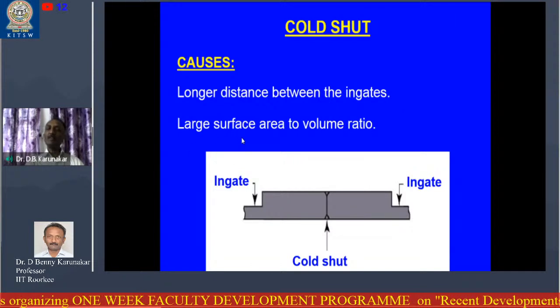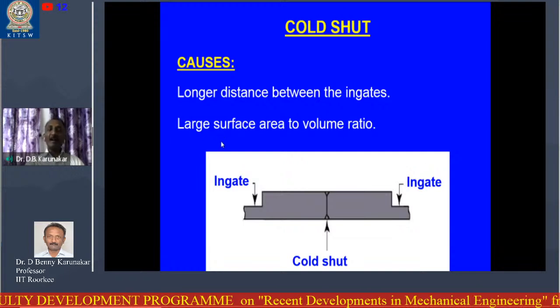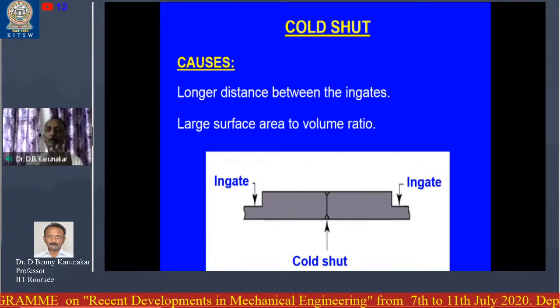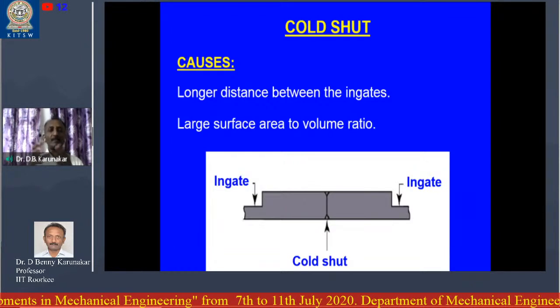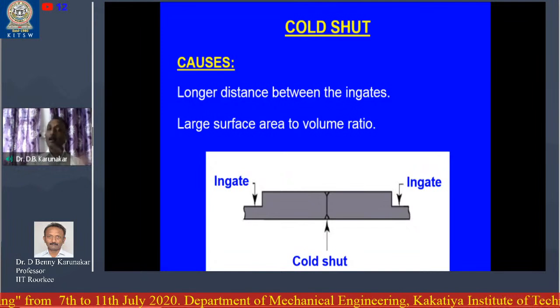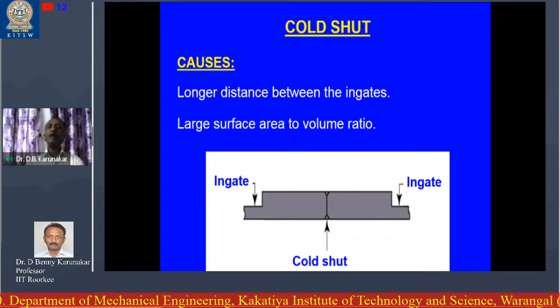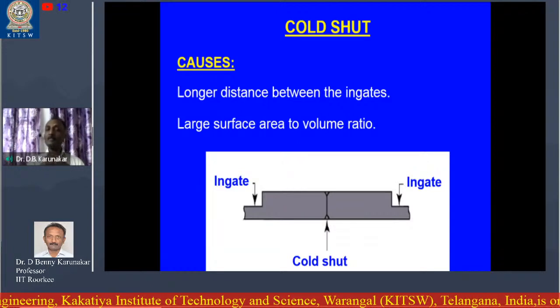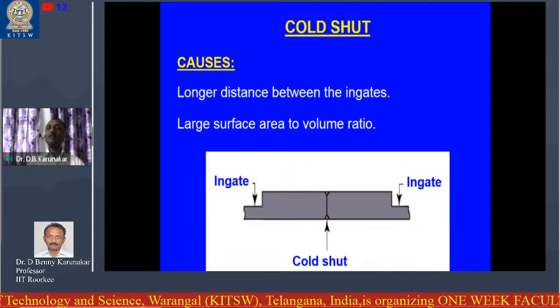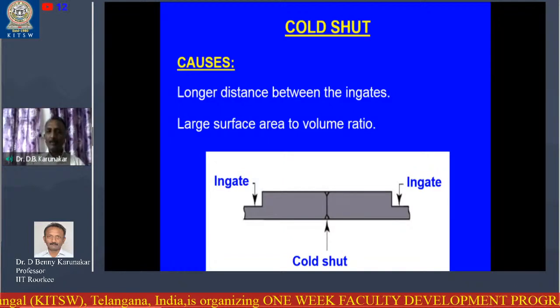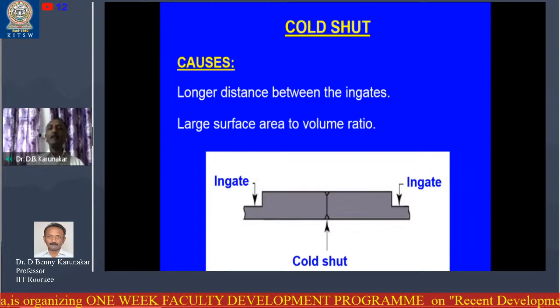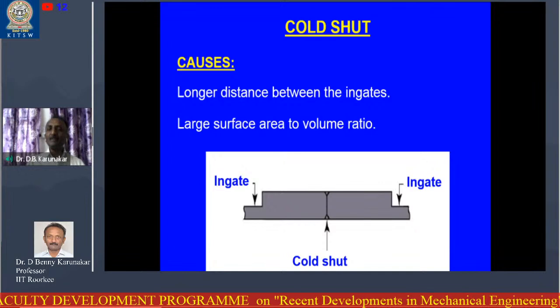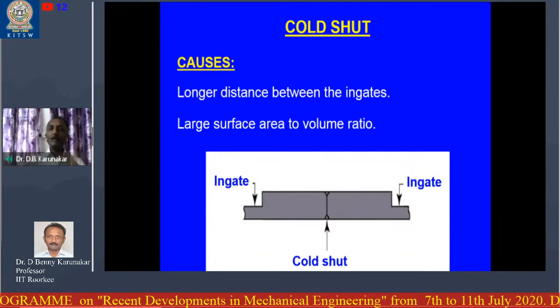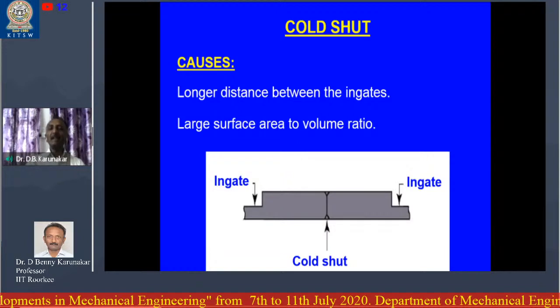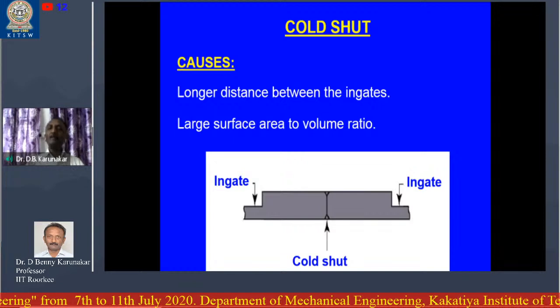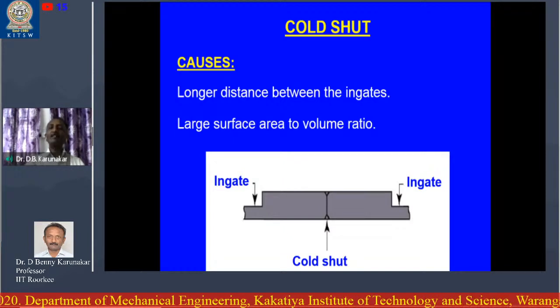Next reason is the geometry of the casting is such that it has large surface area. It is possible that for the same mass or weight of the casting, one casting can have large surface area, another casting can have small surface area. In the first case, the casting having large surface area is in contact with the molding surface, molding sand. So because large surface area is in contact with the molding sand, within short time it will be dissipating heat rapidly to the sand mold, and the molten metal inside the cavity loses its temperature abruptly.